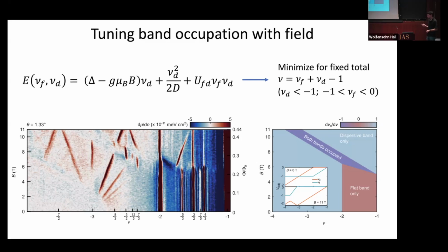But I'll point out that the energy scales are such that actually we are very much in a thermally disordered regime. So if you just think of the exchange t squared over U, t is of order, say, a millivolt or something like that. U is of order 100 millivolts. So t squared over U is tiny compared to the temperature around 300 millikelvin that we're doing these experiments. So we're very much in the thermally disordered limit. Still, you have a huge band gap. So in that sense, the large interaction-driven gap still persists even though you don't have magnetic ordering. So whether you want to call that a Mott insulator or not is up to you. The physical situation is as described.